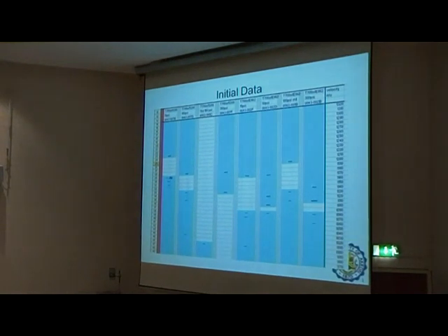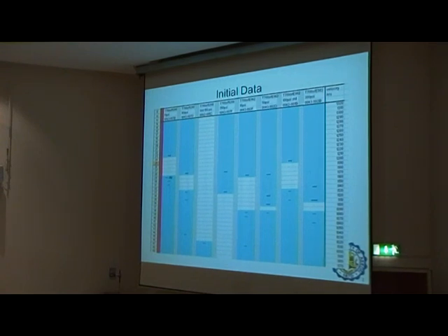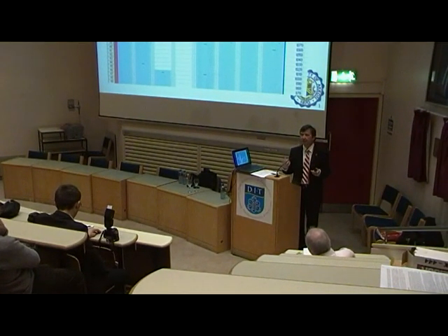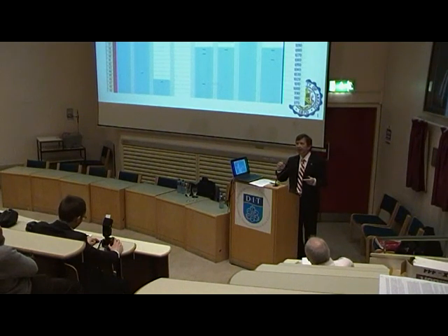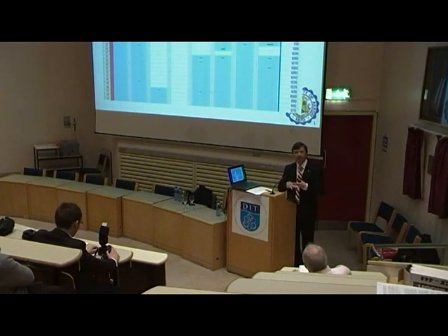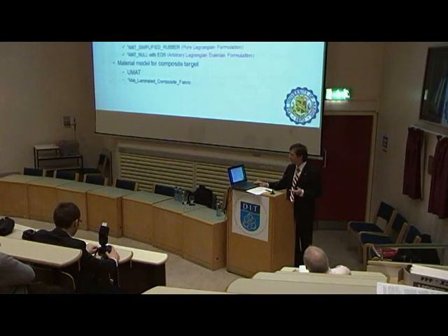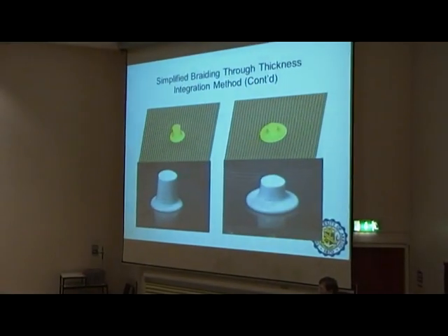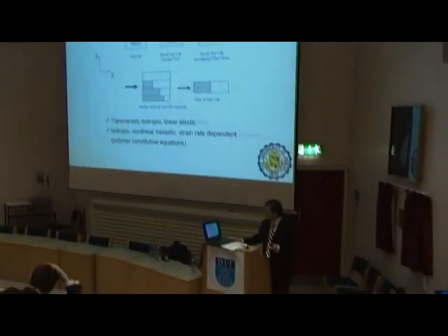fiber, just by changing the matrix, the so-called V50, which is the velocity of penetration, can be significantly different due to the interface strength. In fact, the common sense would tell us that the stronger interface, the better. In fact, in impact, the weaker interface, the better, because the material starts to spread the forces through itself by evaporating or decomposing itself, and fibers, by pulling from the matrix and from the other fibers, can absorb much more energy, therefore it can get much safer for the experiment that we use.